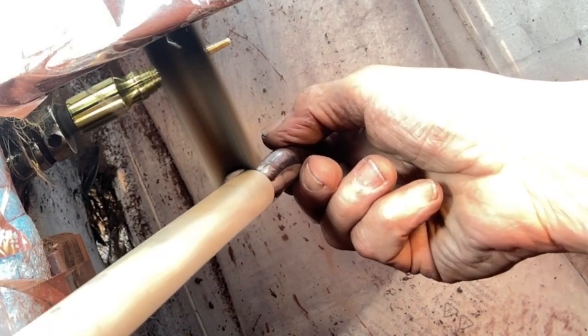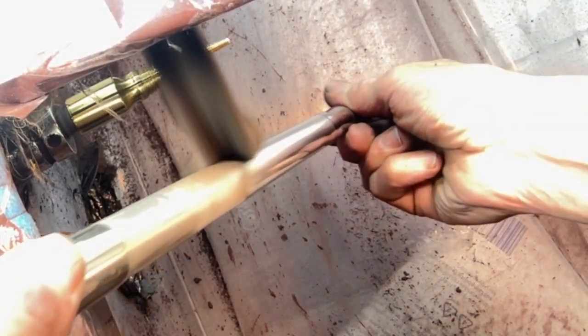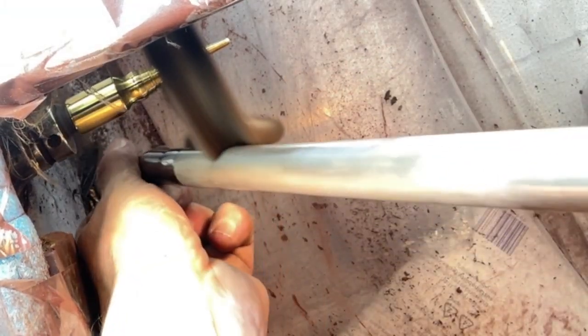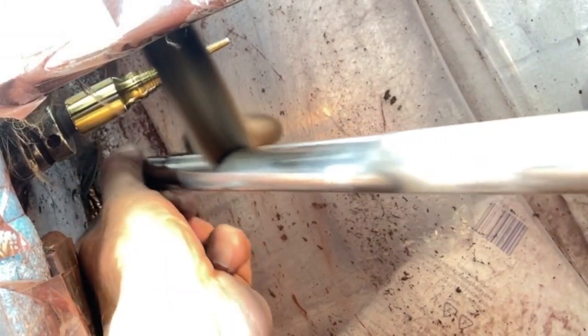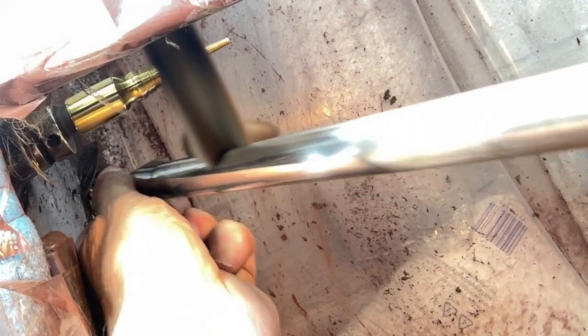All right, so to begin with, I'll use Tripoli. This is the brown compound. And as I said before, I want to keep crossing my angles. I'll work lengthwise as much as possible at a slight angle to the left, and then I'll work lengthwise with a slight angle to the right. I do very, very little crossways polishing because I can put in a dip so easily. And when I've finished enough of that, we'll do some lengthwise polishing. So it's starting to get a good surface.